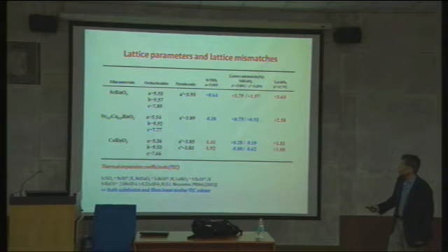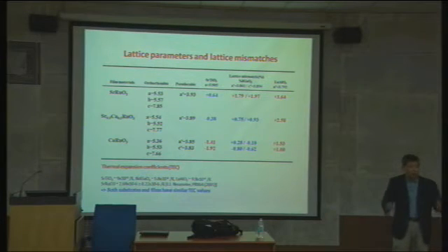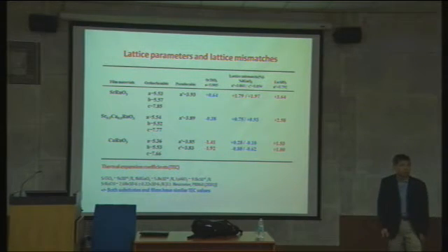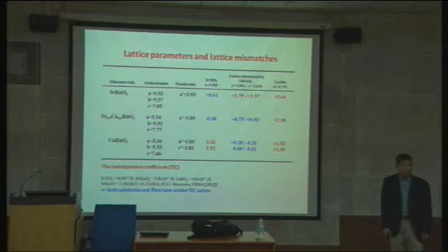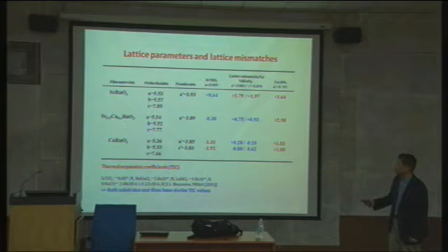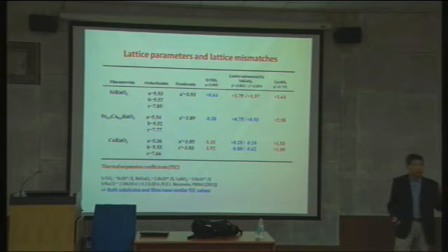Calcium ruthenate has a lattice parameter of roughly 3.85 angstrom. You have two different directions, it's different because of the orthorhombic structure, but roughly 3.84 on average. You have roughly 3.93 versus 3.83, like a 0.1 angstrom difference. That's quite big from a lattice point of view. And why is this different? The strontium is bigger, calcium is smaller.